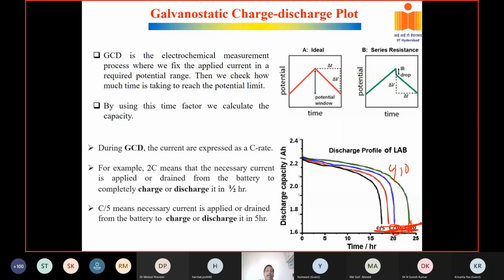As I told you, from the Peukert plot you can calculate the current. Once you do 1C rate, exactly 1 hour you should get, and once you do C by 20 rate, exactly 20 hours you should get. Then you plot it, you get a straight line, and you can calculate the current at a particular C rate. So what it gives us is the voltage profile.